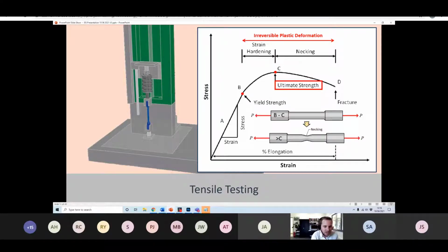Anyway, before we settle on the definitions for strength, it's maybe important to highlight what's actually going on between points B and C during a tensile test, because during this particular stage, the tensile test specimen is straining, or stretching if you like, but it's doing so uniformly, which really just means that as the specimen gets longer, the cross-sectional area is getting smaller too, but it's doing so uniformly, i.e. the cross-sectional area is the same at every instance, all the way down the length of the central section of the testing coupon. Okay, so that is uniform plastic straining or uniform elongation of the specimen.